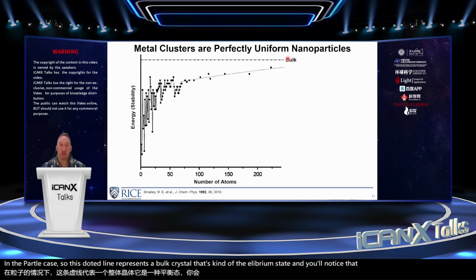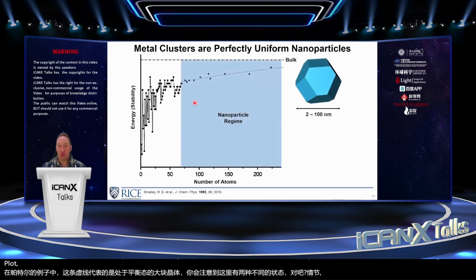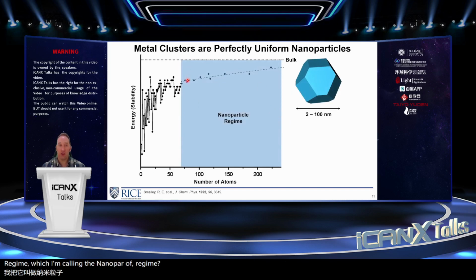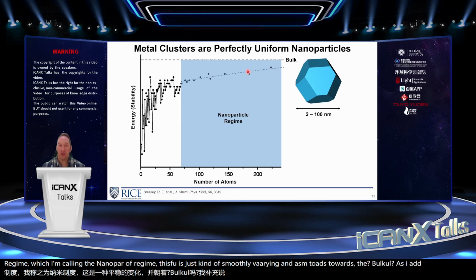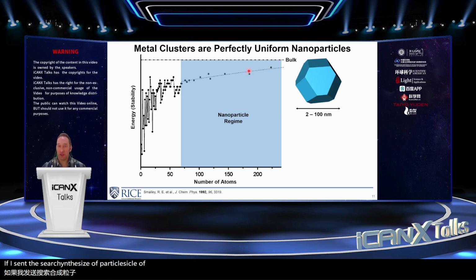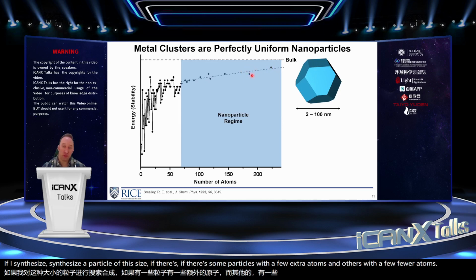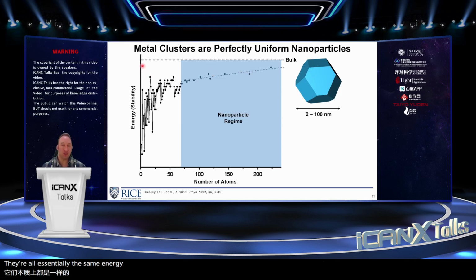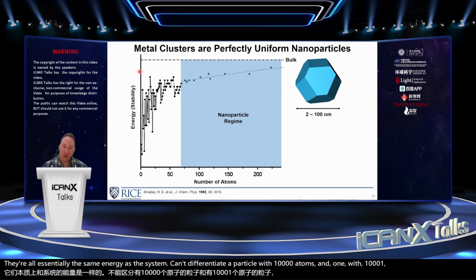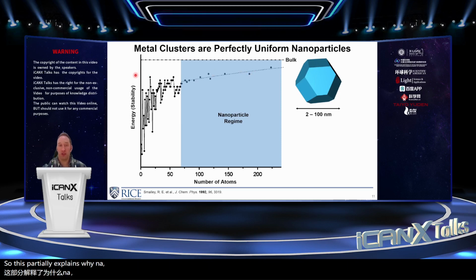And you'll notice that there are two distinct regimes on this plot. So this first regime, which I'm calling the nanoparticle regime, this function is just kind of smoothly varying, asymptoting towards the bulk as I add atoms. If I synthesize a particle of this size, if there's some particles with a few extra atoms and others with a few fewer atoms, they're all essentially the same energy. Okay, so the system can't differentiate a particle with 10,000 atoms and one with 10,001 atoms. So this partially explains why nanoparticles are intrinsically uniform. There just are not differences strong enough for the system to differentiate them. Okay, so these are nanoparticles.